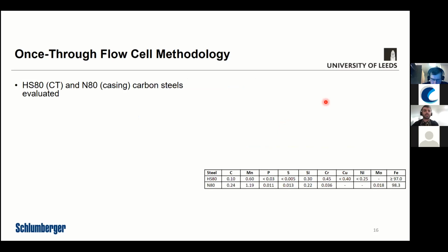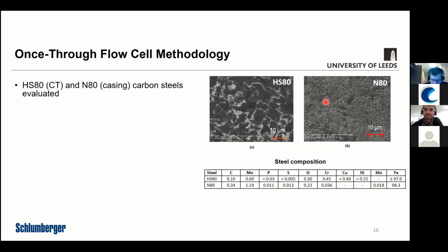So to give you an overview of the methodology, we looked at two different carbon steels. So we've got HS80, which would be the coiled tubing material, and N80 carbon steel, which would be common as the casing material. You can see you've got various different compositions of those two steels and slightly different microstructures. And obviously it's important to evaluate both of those. Like I said, the acid is exposed to any sort of materials in that environment during the matrix acidizing procedure. So we need to know how effective the inhibition methodology is, not just on some metals, but as many as we can characterize as possible.